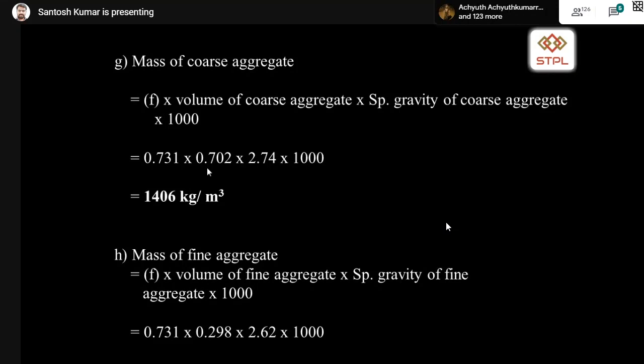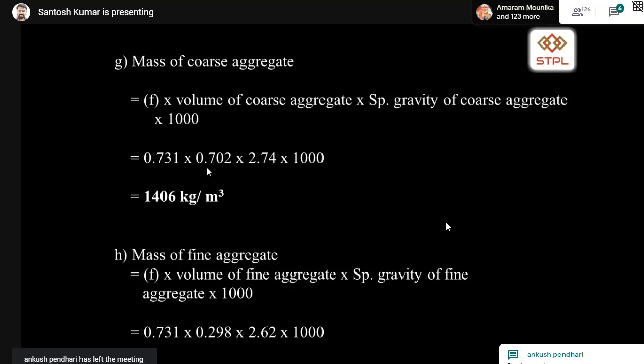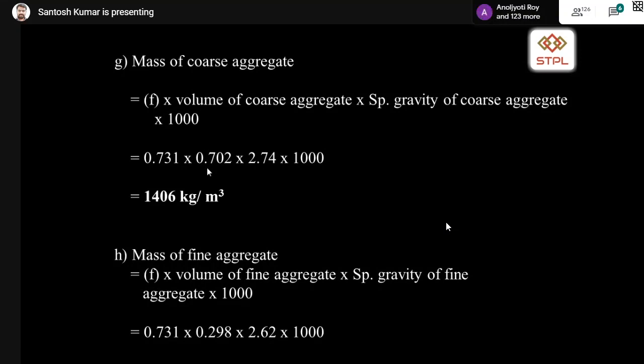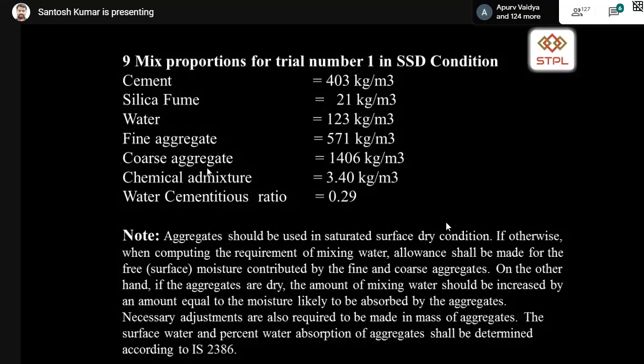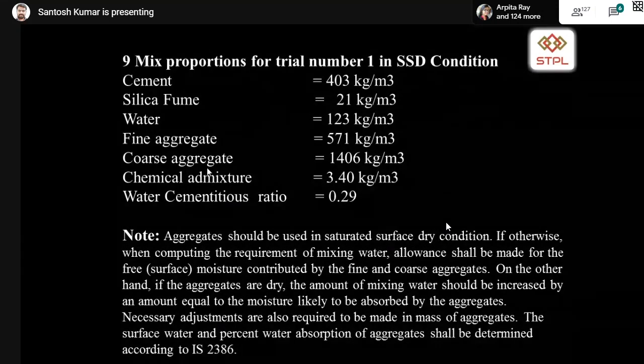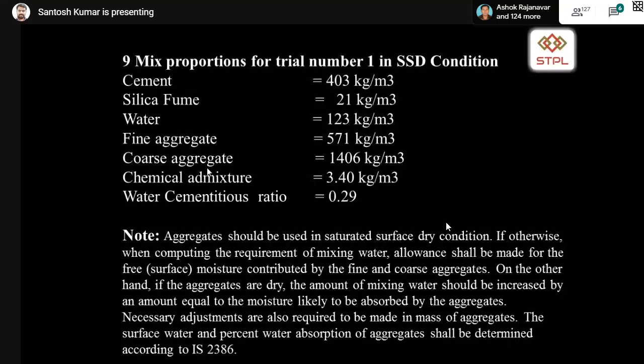Mass of fine aggregate is again the all-in aggregate volume, which is 0.731, multiplied by the volume fraction of fine aggregate, which is 0.298, multiplied by specific gravity of fine aggregate, which is 2.62 considered, multiplied by 1000. That gives you the weight of fine aggregate as 571 kg per cubic meter. That's it. Your high strength concrete design is completed. Cement content 403, silica fume 21 kg, water 123 kg, fine aggregate 571, coarse aggregate 1406, chemical admixture 3.4 kg per cubic meter, water cement ratio 0.29. Your mix design is completed.